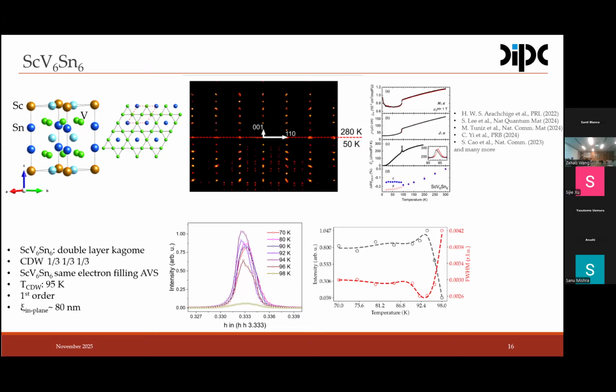The compound has a charge density wave with propagation vector 1/3, 1/3, 1/3, below 95 to 100 Kelvin. There are anomalies in transport, like resistivity and magnetization, and also a small peak in the specific heat. This 1/3, 1/3, 1/3 point is not a high symmetry point in the Brillouin zone. The 1/3, 1/3, 1/2 is the H point, and 1/3, 1/3, 1/3 is between K and H. In principle, we don't expect anything electronically there. So it has the same filling as the 135 cesium vanadium. The charge order transition is around 95 Kelvin, which oscillates between 92, 95, and 100, depending on the quality of the sample.